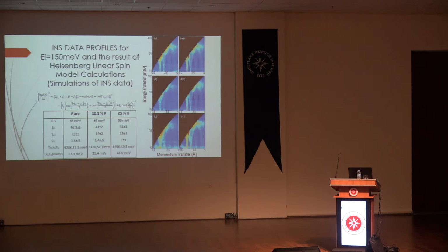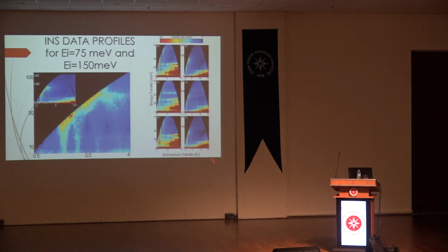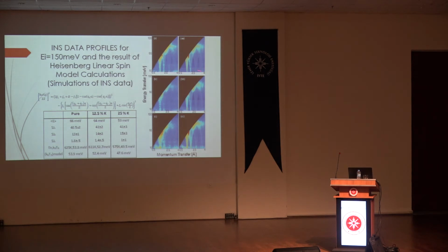To define a background, the definition is basically moving to a high Q value where everything is phonon dominated, and carrying that to the low Q value region by scaling it. As I said, the intensity goes quadratically, Q to the power 2. When you average, for example, 10 to 15 Q, the intensity in this line, and carry that intensity there by dividing by Q to the power 2 values, you may subtract here and get more intensity for the magnetic one. Or the way that I did, you basically calculate the magnetic information and put it on the background and find almost the same fitting behavior.